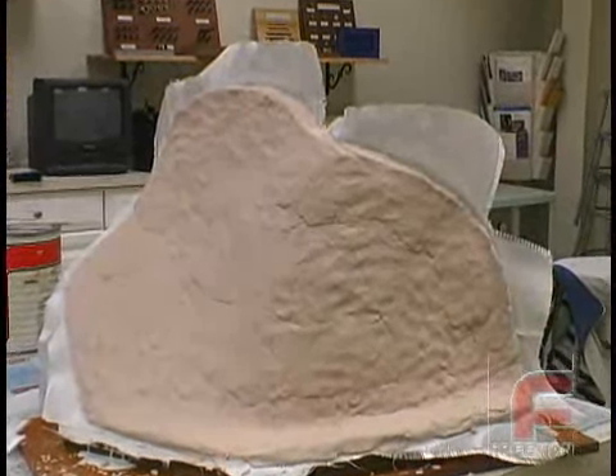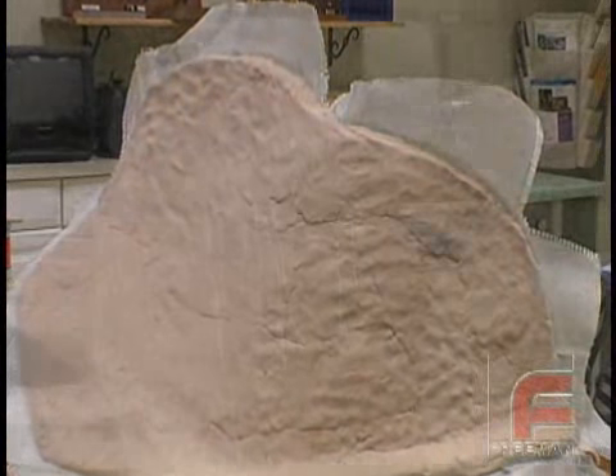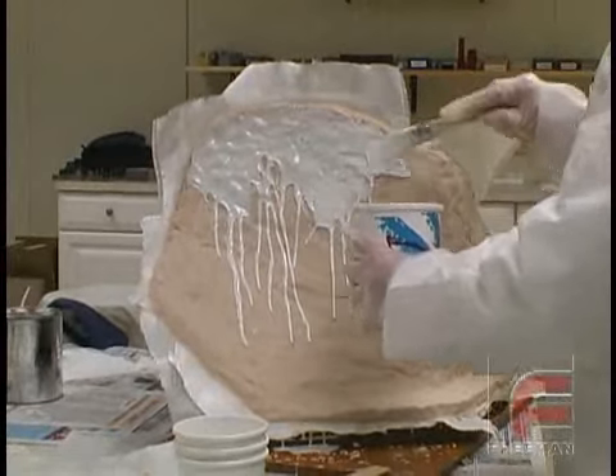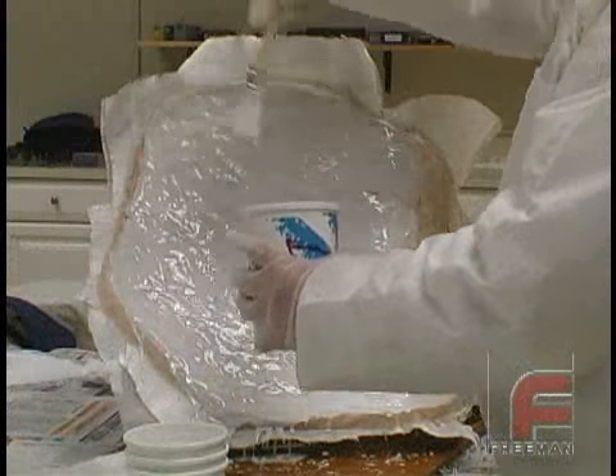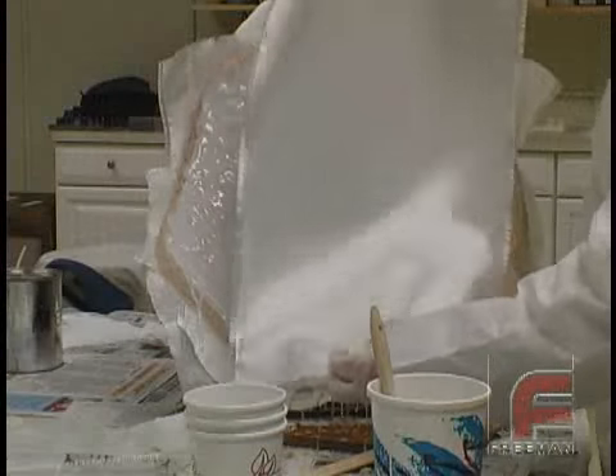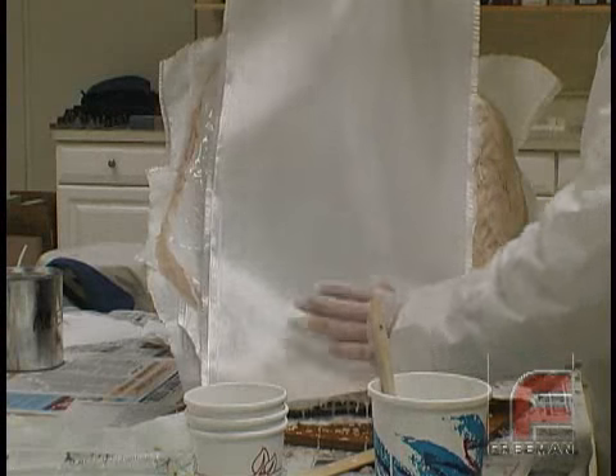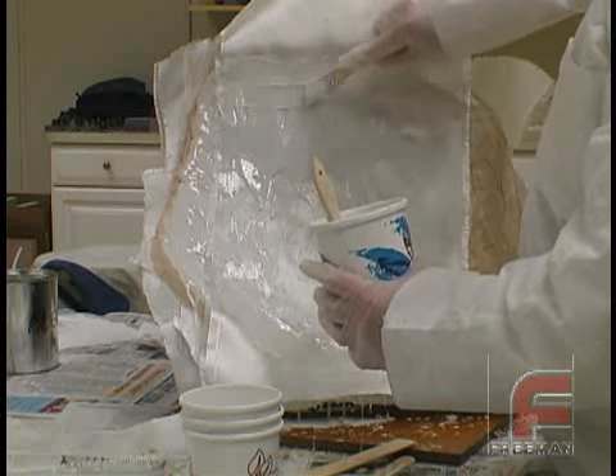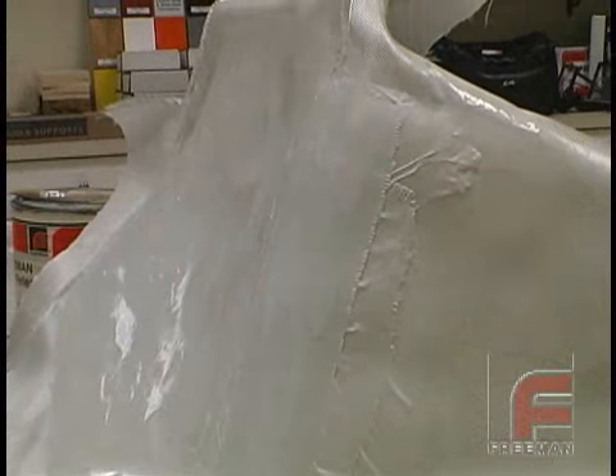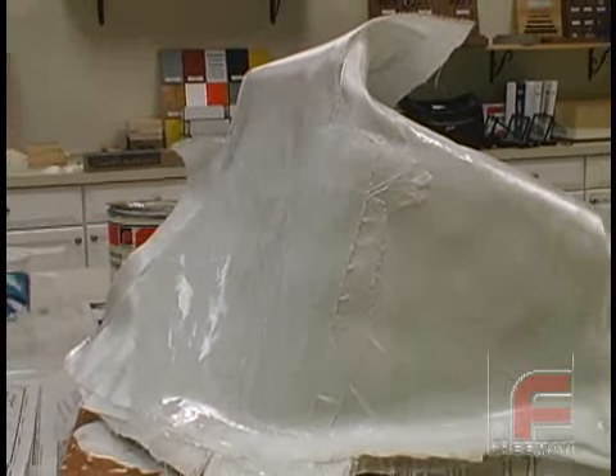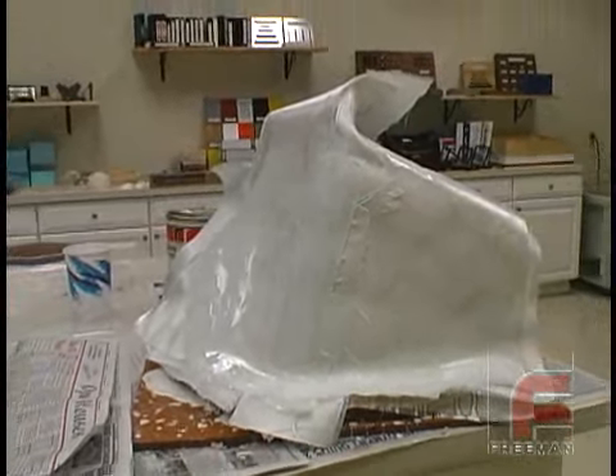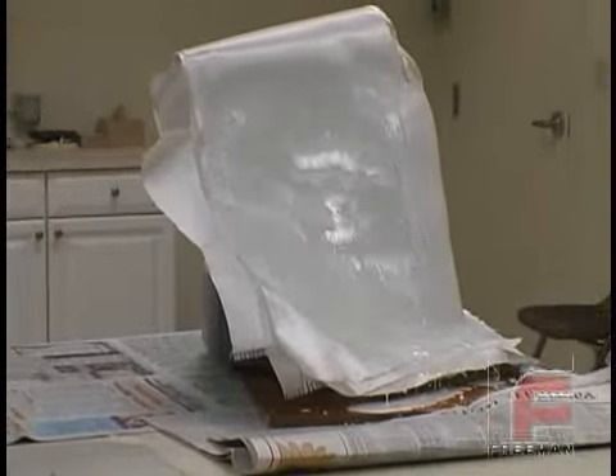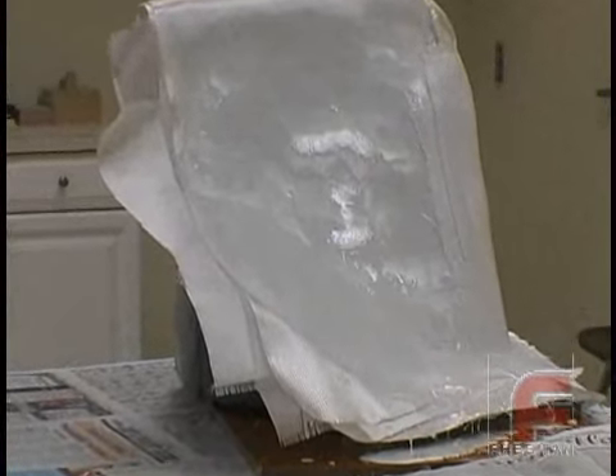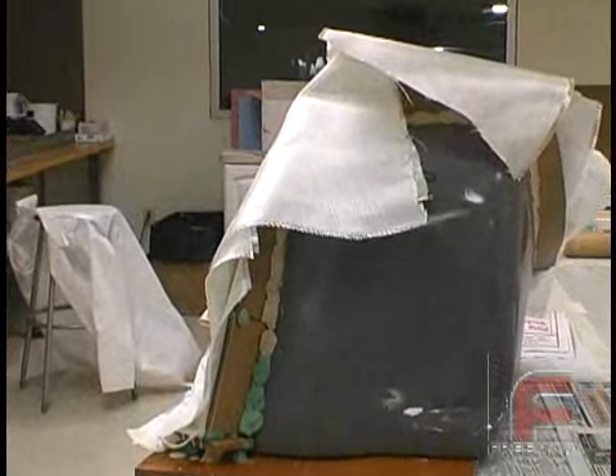Here is our finished application of the paste laminate. We are now ready for our final three layers of fiberglass cloth, beginning with our laminating resin. We do not have to wait until the paste laminate hardens before applying the final layers of cloth. Our first part is now complete and ready to cure overnight. If we had been following the epoxy laminating system, we would still be laying up our maximum of 12 layers of fiberglass cloth per day and then have to finish up the part tomorrow to add the additional layers required to build a strong tool.